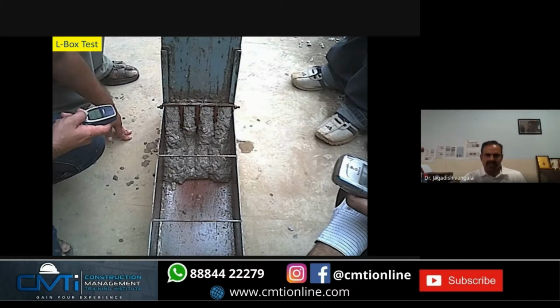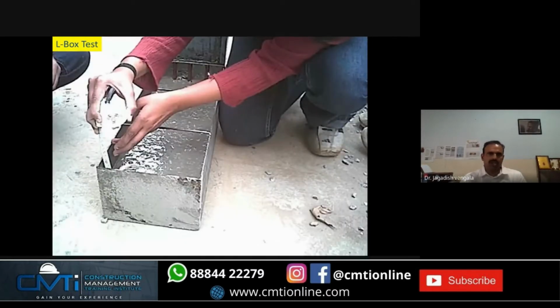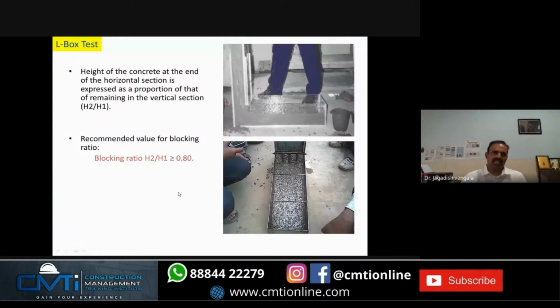So you fill the vertical box, lift the gate, and then it has to pass through the reinforcement. There is an indication at 200 mm and 400 mm. You measure the times, and also the height difference between both the ends, H1 and H2. H2 by H1 we call the blocking ratio, and it should be more than or equal to 0.8. What does that mean? The height difference should generally be flat. Otherwise, the difference should be less.